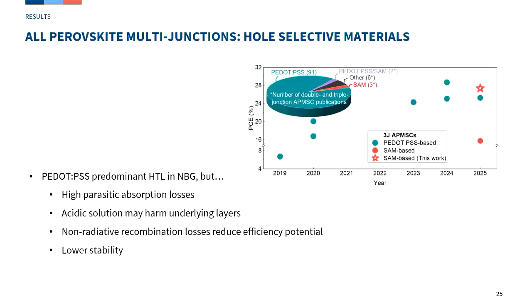There's a drawback: if you look into the literature, typically people use so-called PEDOT:PSS, which is a very nice material, typically used for anti-static coating. If you peel off a foil from a screen, very likely there is PEDOT:PSS on top of it. However, it has drawbacks—it's absorptive, very acidic, and has very strong recombination in contact with the perovskite.